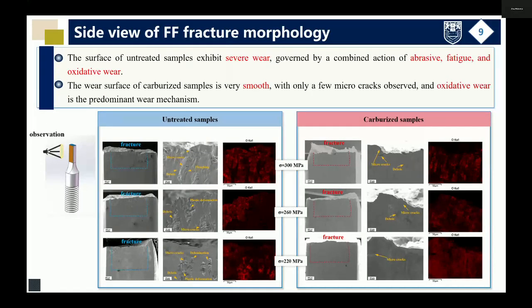Next, we examine the fretting wear surface by SEM and EDS. For the untreated samples, the surface shows severe damage. We can observe microcracks, ploughing, plastic deformation, and debris. In addition, EDS analysis indicates the presence of oxidative wear. So, the wear mechanism is governed by a combined action of abrasive, fatigue, and oxidative wear.